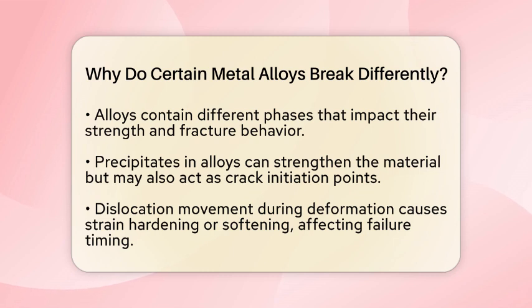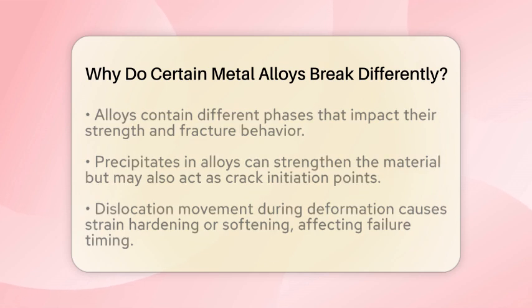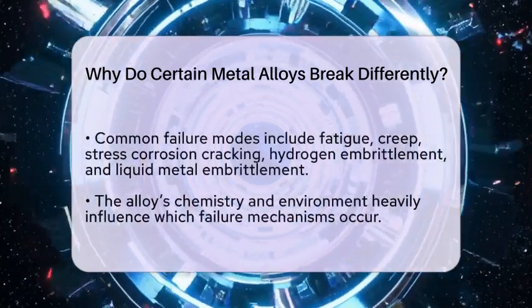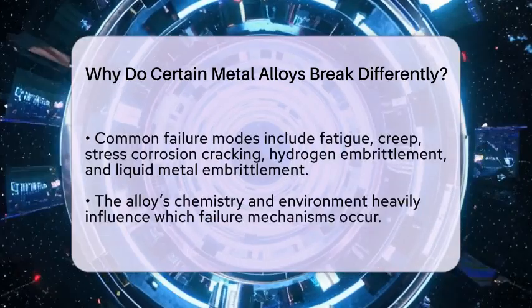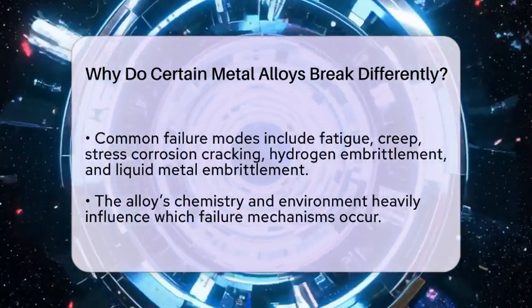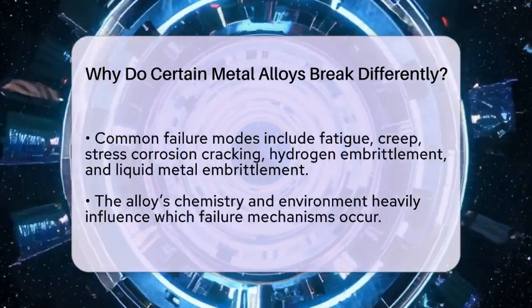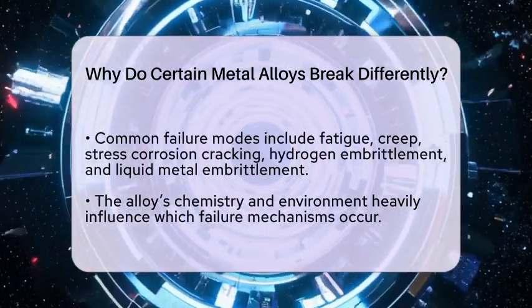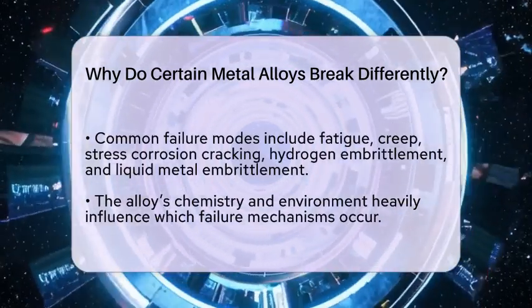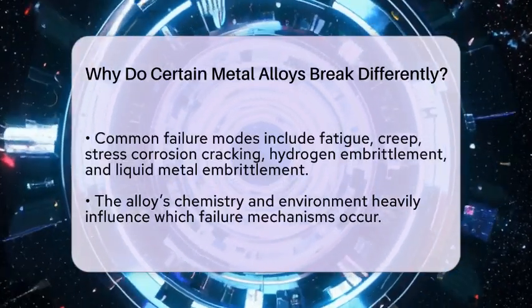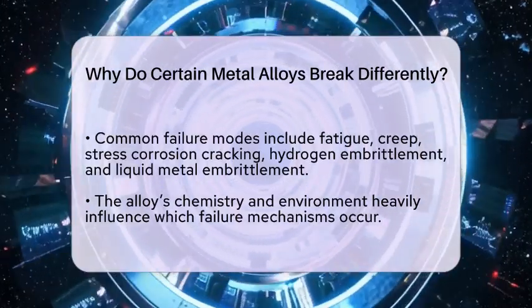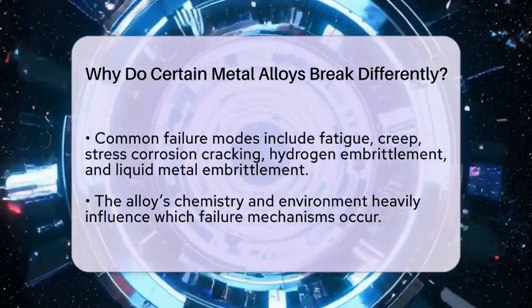Fatigue occurs when repeated stress causes tiny cracks that grow over time. Creep is slow deformation under constant high temperature and stress. Stress corrosion cracking happens when a corrosive environment and tensile stress combine, causing cracks along grain boundaries. Hydrogen embrittlement involves atomic hydrogen weakening the metal, making it brittle. Liquid metal embrittlement occurs when a liquid metal, like mercury or aluminum, causes rapid cracks along grain boundaries under stress. These failure mechanisms depend heavily on the alloy's chemistry and the environment it faces.